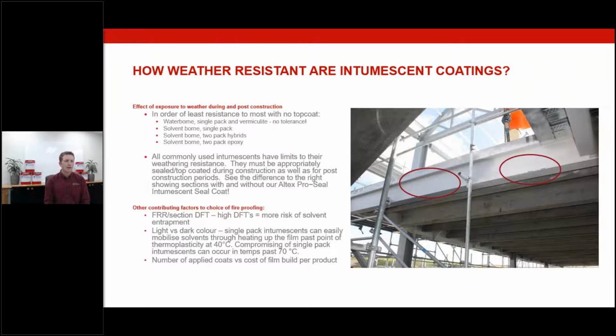We quite often see a combination of solvent entrapment with your dark colors. So any dark colors on intumescent systems that are not fully cured are easily compromised, and you'll easily recognize those through large blistering on intumescent coated faces, especially northern facing sides, for obvious reasons. And you'll easily cut open that film and you'll get a face full of solvent coming out of that particular material, and that's usually the root cause.